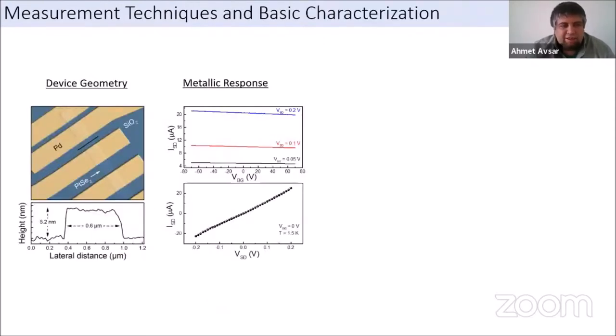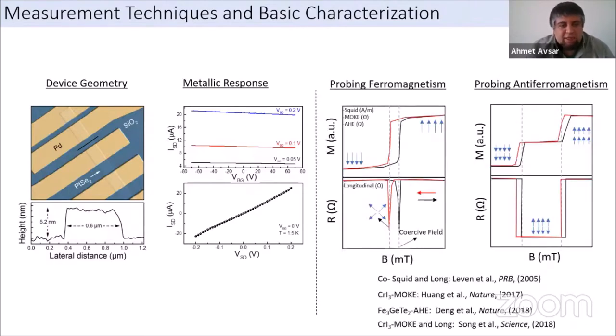Okay, and then we started to make the devices, and I will tell you in a minute, but we need to do a comparative study as a function of thickness. Therefore, we wanted to have the same width in all the crystals that we study. And also sometimes we were not seeing the magnetic response that I will be showing in a minute in the wider samples. So that's why we chose only the materials which have a width of less than a micron. And this was the first sample we indeed studied, and it shows the metallic response as we expect, because the thickness is about 5.2 nanometers, and we started doing the magnetic measurements.